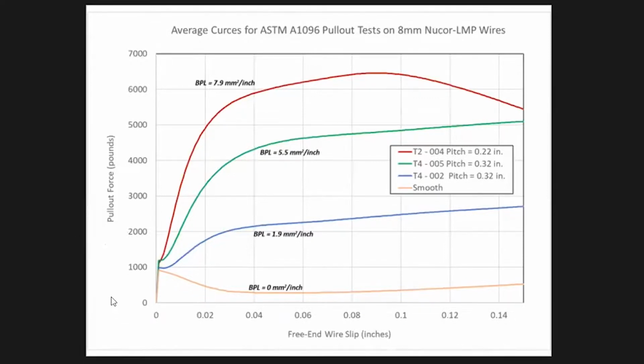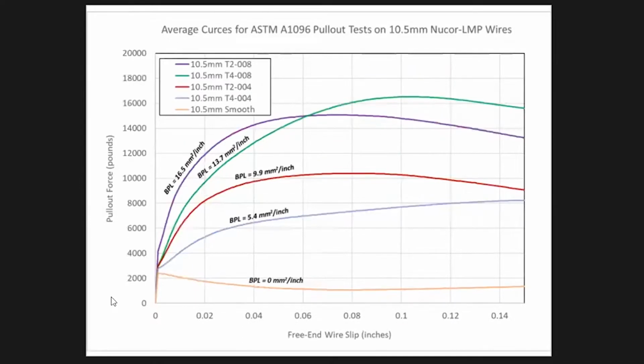And notice why I'm so excited about this parameter: the bite per length has direct correlation with the bond. The higher the bite per length, the steeper the bond. It works out. So this 0, this is a smooth wire. Smooth wires behave really differently. As soon as we break bond at the top, we're adding tension to this wire. It's not pre-tensioned. So now that wire is trying to get smaller in diameter. So once we have relative movement, the force drops off. But as we add indents, the deeper we go, the more bite we give, the higher the bond. Same thing for the 10.5mm wires. Again, the smooth wire down here. And as we increase bite per length of those wires, the bond increases.